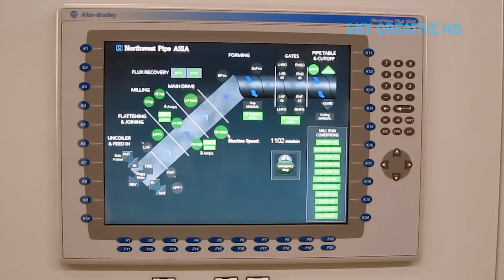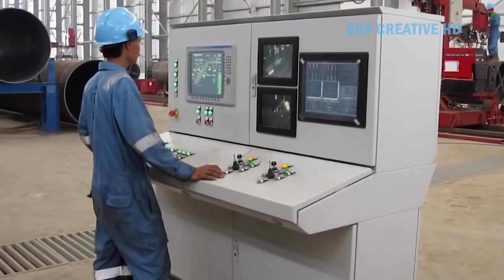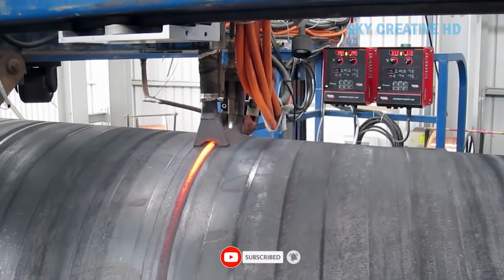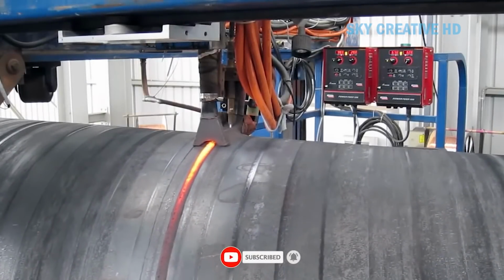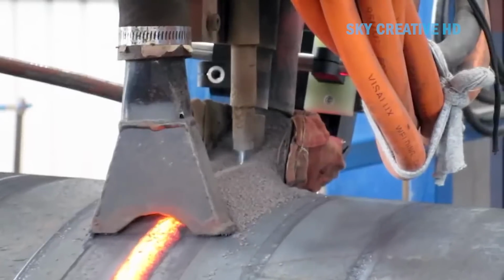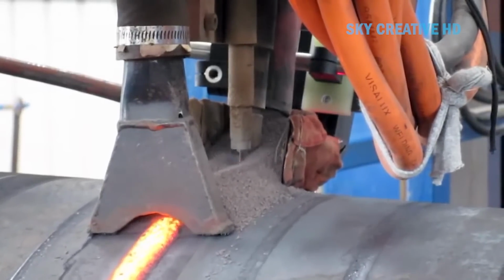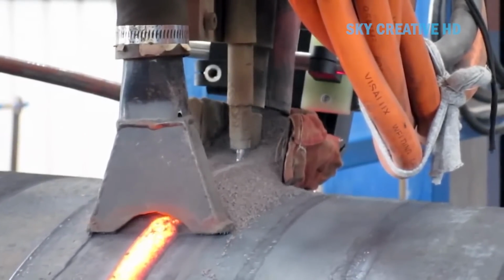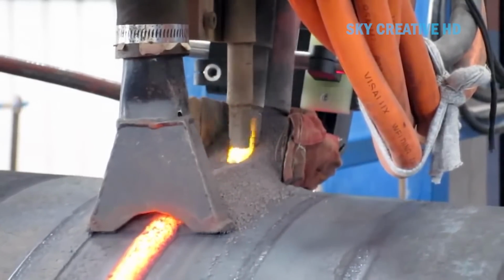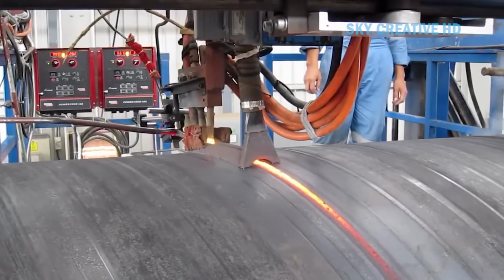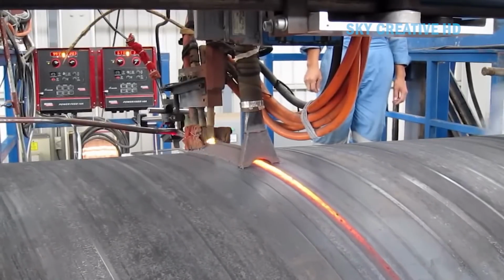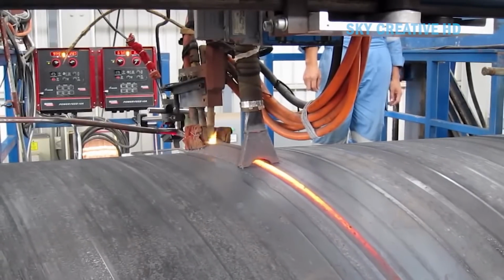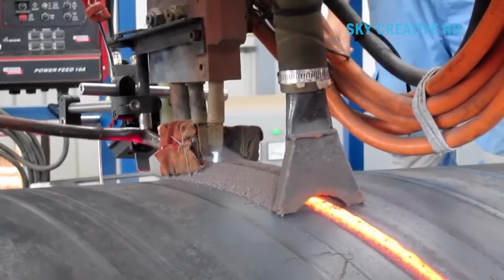Immediately following the forming rollers is the welding station. Here, the meeting edges of the strip are continuously joined. The most common welding process for thicker materials is submerged arc welding (SAW), where a consumable electrode is buried under a granular flux, creating a protective slag. For thinner materials, gas metal arc welding (GMAW/MIG), which uses a consumable wire electrode shielded by an inert gas, is often employed.